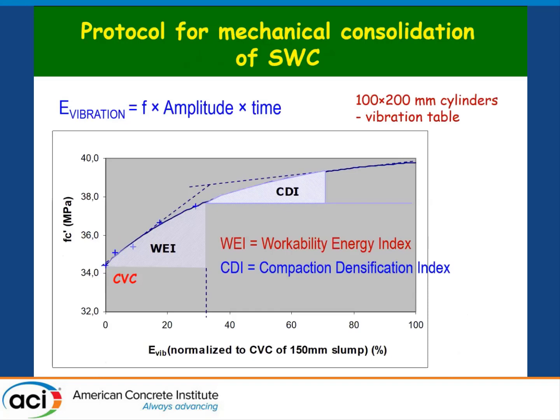And then what we did is we wanted to relate the compressive strengths that we are obtaining to the consolidation energy. So we calculated the vibration energy as the frequency of the vibrator, this is a table vibrator, multiplied by the amplitude, multiplied by the time. So the only thing that we change here is how many seconds those 4x8 cylinders were vibrated on the vibrating table. And after different seconds, we calculated the energy.